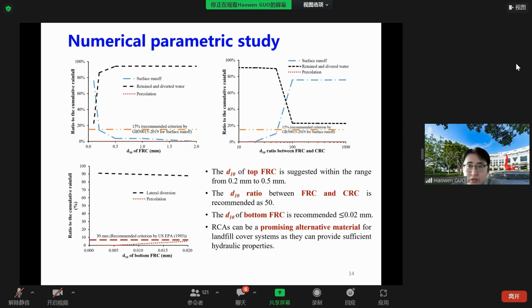We also carry out some parameter studies to optimize the combination of the particle size we used for the current system before we use them in the field site. The top left figure shows that the surface runoff decreased sharply as the D10 of FRC increases from 0.1 millimeter to 0.5 millimeter. So with the improvement of D10 of FRC, the surface runoff reduced gradually to 0, but the rainfall water into the landfill cover would transfer to water storage and infiltrated water into the deep soil layer.